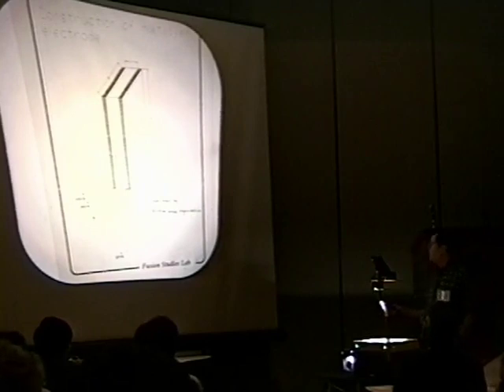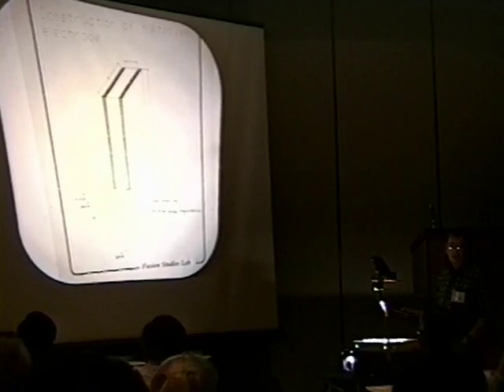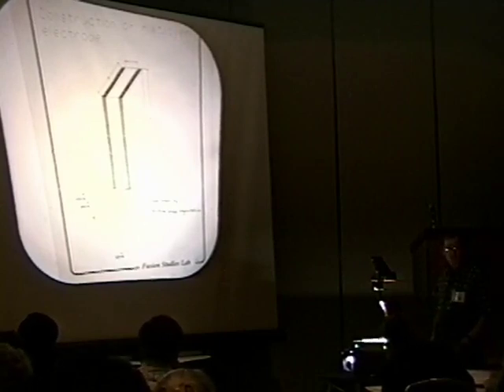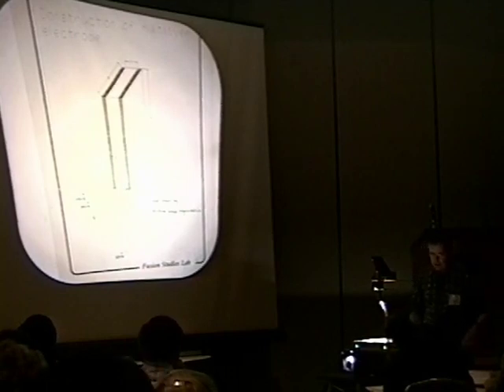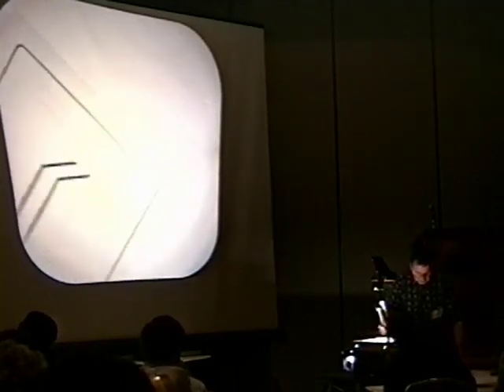First, using electron beam vaporization techniques, we have laid down thin films of the type I just showed, palladium, titanium, and so on, 100 angstroms thick each, on both sides of a stainless steel substrate to provide strength. And we put on the outside a 60 angstrom film of chromium. The chromium was our attempt to provide a barrier to help sustain the deuterium density internally.